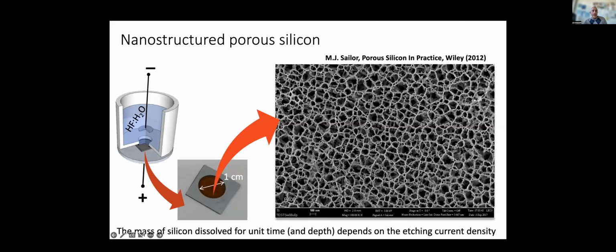And as Ciro explained very well in his talk, porous silicon is an amazing material because you can fabricate it very easily by electrochemical etching of a crystalline silicon substrate. You can tune the etching parameters to control the porosity. At the nanoscale, we cannot really control the pore position, but we can control the porosity. So the mass of material removed per unit time, and this value depends basically on the etching current density flowing through the electrochemical cell. So by changing the etching current density, I can change the mass of material removed per unit of depth.